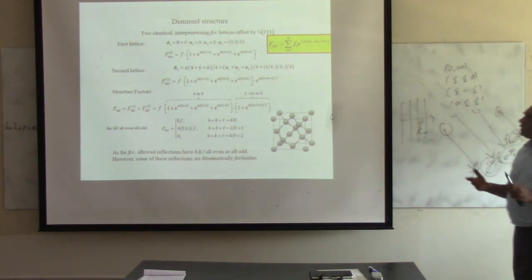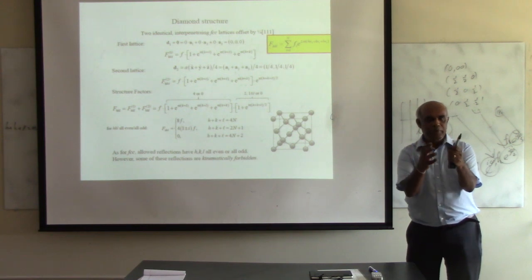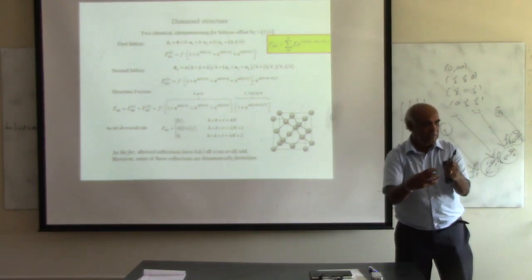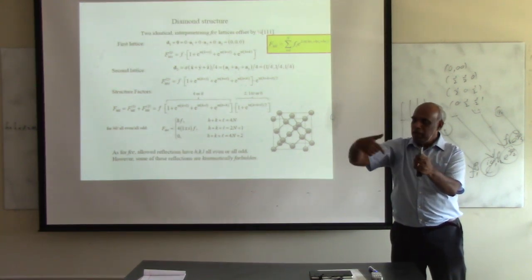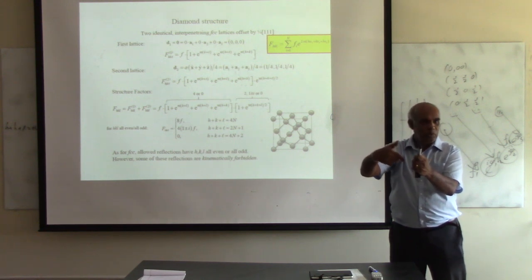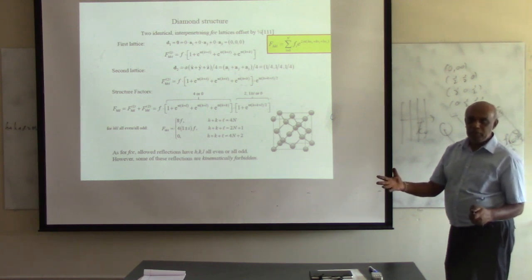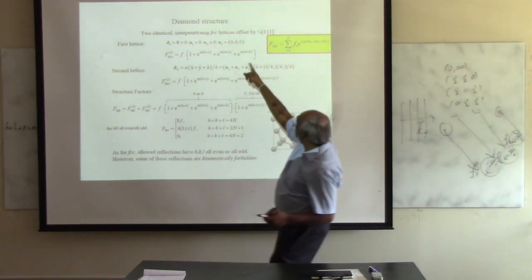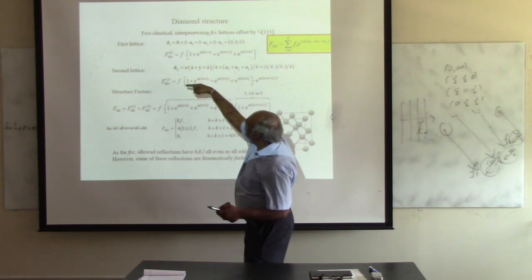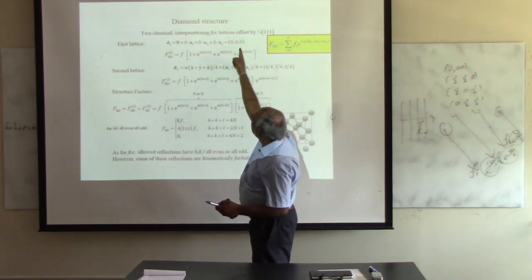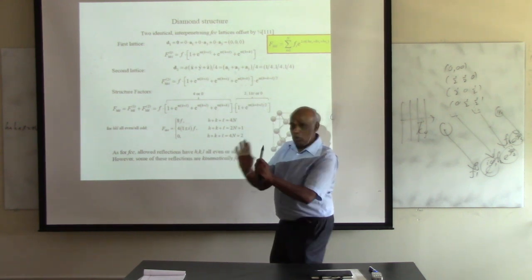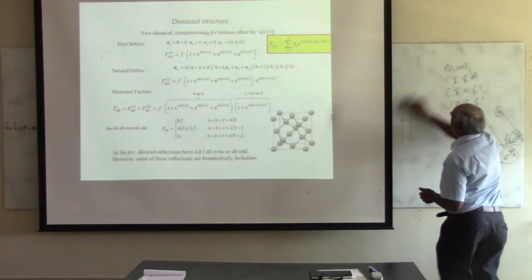So now if you consider diamond. So diamond, what is the situation? Like I said, diamond is more like 2 FCC lattices you just interlace, right? You can push it in the diagonal direction by quarter distance, right? That means you have 8 atoms. So here I just put it in a different way, like 2 different lattices, one at 0, another one shifted by quarter. Or you can write 8 atoms.